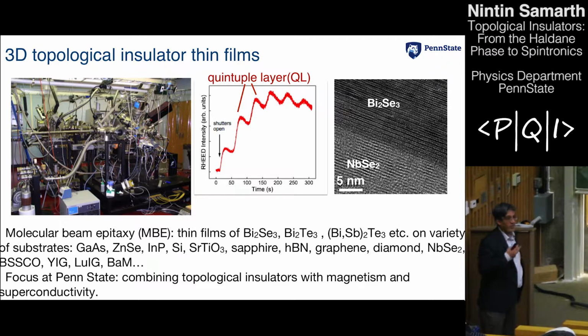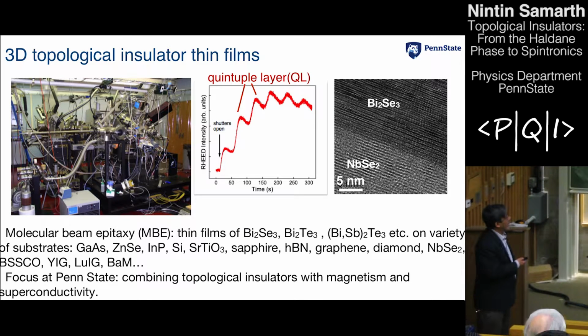We evaporate the various elements, and as we evaporate the various elements, we can monitor the surface by using electrons that are reflected off the surface of the sample, high-energy electrons, about 15 kilovolts. And we can monitor diffraction patterns, but we can also monitor the layer-by-layer growth. It's sort of like playing atomic scale Legos, where you can monitor the growth of one unit cell. In this case, this is one quintuple layer. There are 5 atomic layers that are formed during these oscillations.